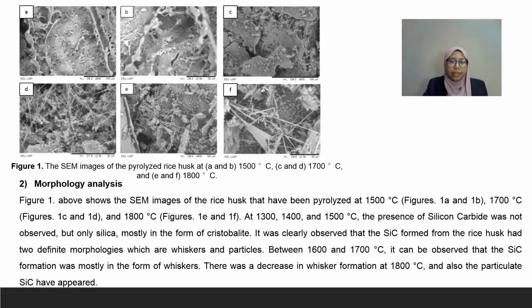Figure 1 above shows the SEM images of the rice husk that has been pyrolyzed at 1500 degrees Celsius for figures 1A and 1B. For figures 1C and 1D, the rice husk was pyrolyzed at 1700 degrees Celsius. Meanwhile, for figures 1E and 1F, it was pyrolyzed at a temperature of 1800 degrees Celsius. At 1300, 1400, and 1500 degrees Celsius, the presence of silicon carbide was not observed, but only silica, mostly in the form of cristobalite. It was clearly observed that the SiC formed from the rice husk had two definite morphologies, which are whiskers and particles.